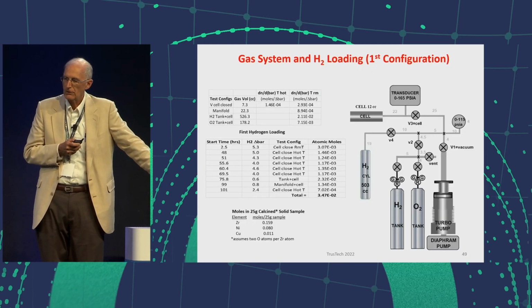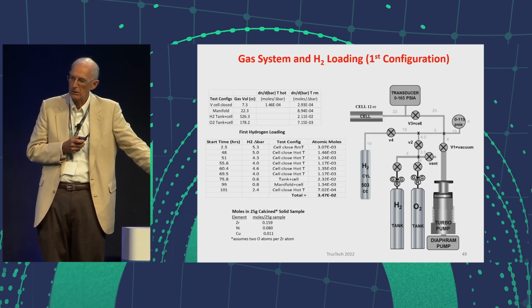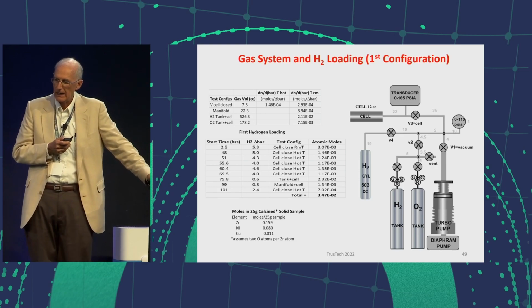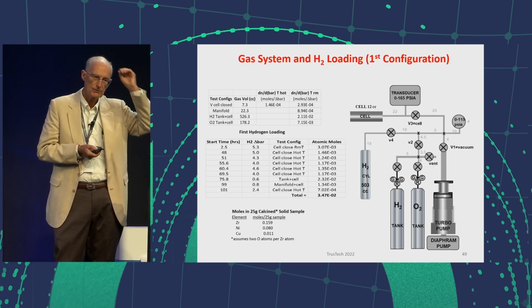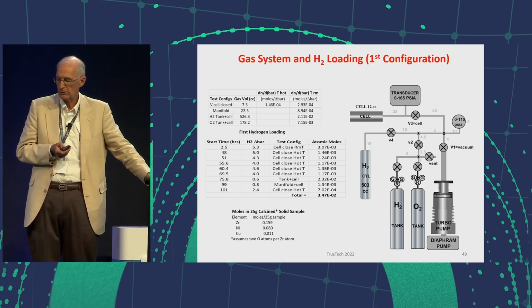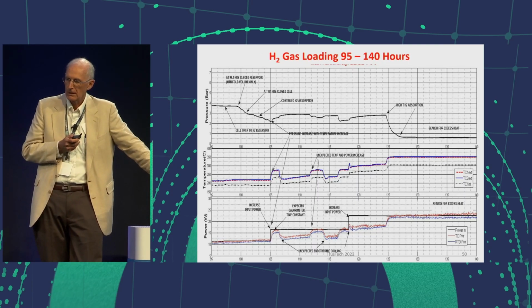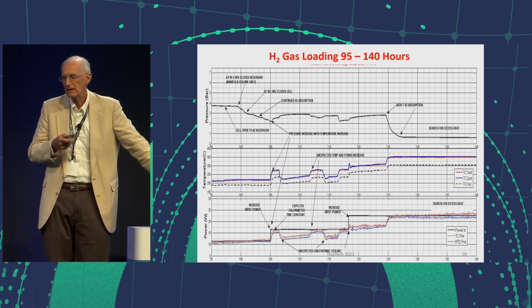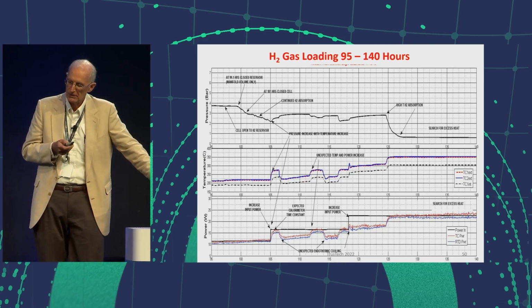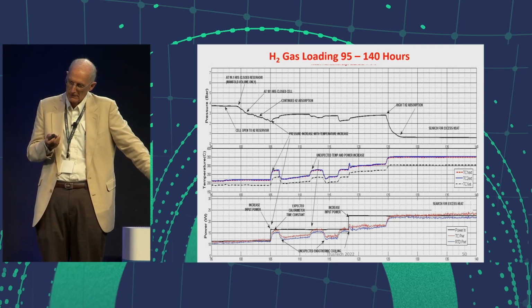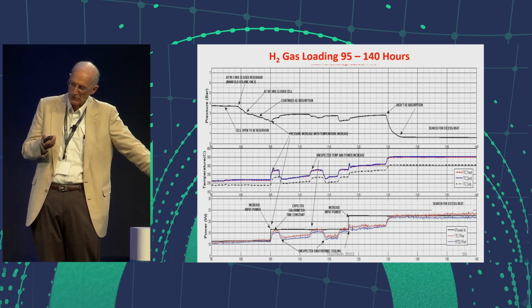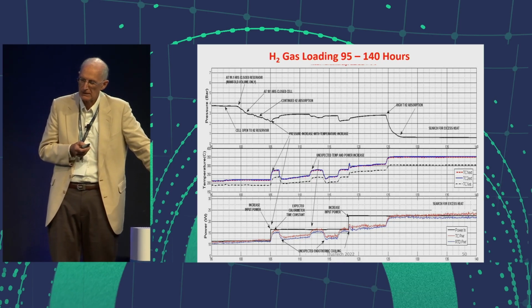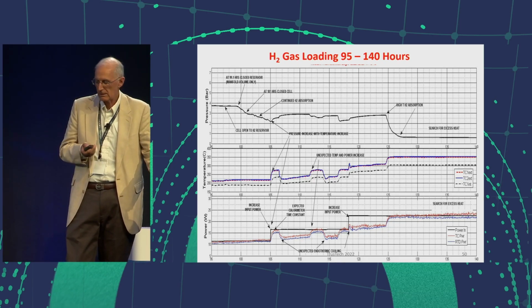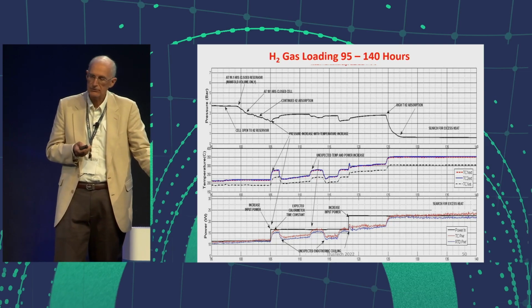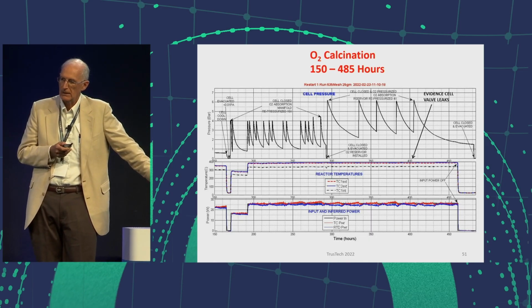This shows the gas system for the H2 loading, and the amount of atomic hydrogen that was loaded in by the various pressurizations. This actually emphasizes that end of the data run in the bottom curve, emphasizing where you see the endothermic reaction. But again, there was no excess heat that was observed.